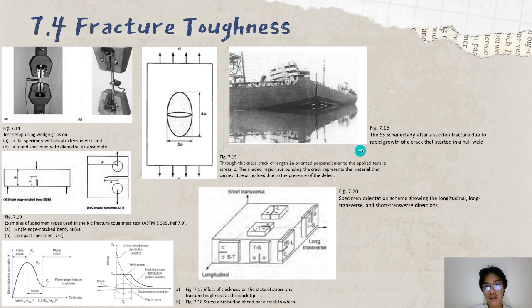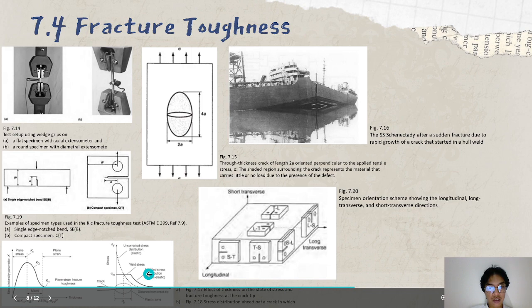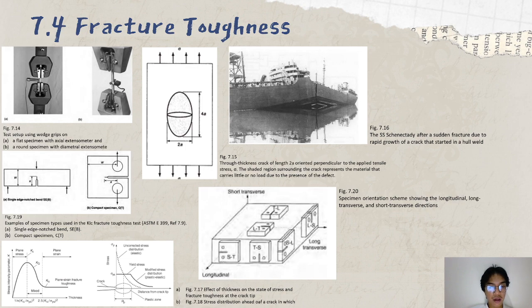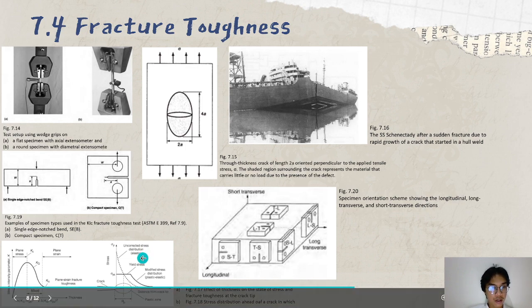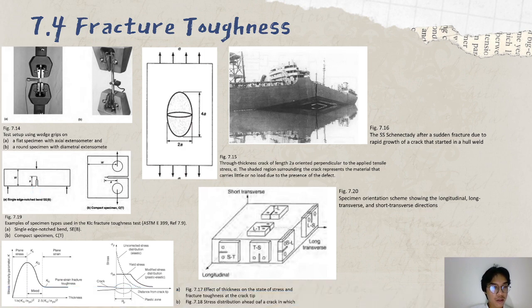In 7.16 is the ship after a sudden fracture due to rapid growth of a crack that started in a hull weld. In 7.17 A is the effect of thickness on the state of stress and fracture toughness at the crack tip. In 7.18 is the stress distribution ahead of a crack. In 7.19 is an example of specimen types used in the KIC fracture toughness test, ASTM E399.